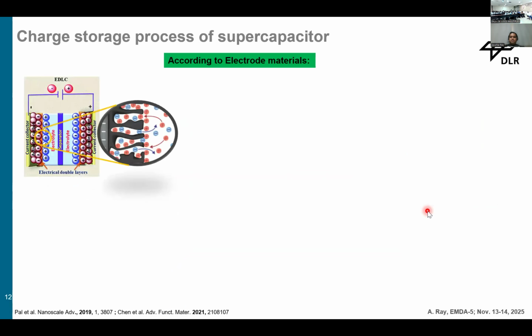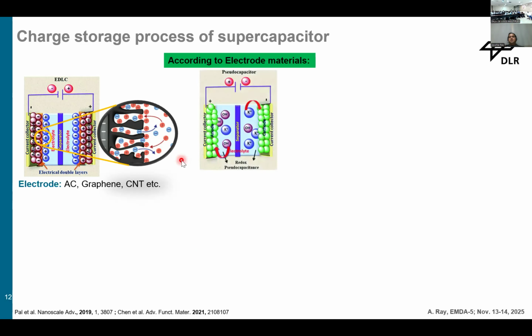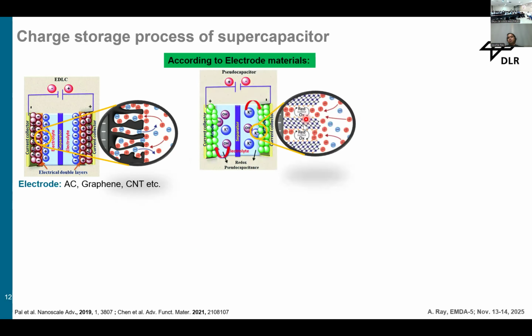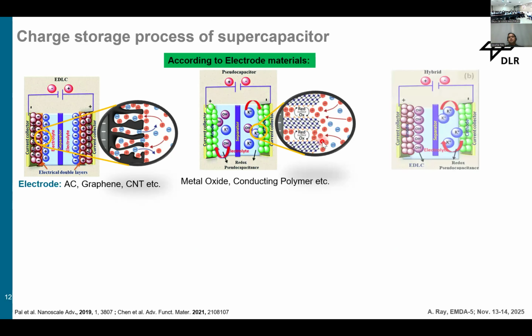Charge storage process in supercapacitors depends on the materials. In carbon based material, charge is stored in an electrostatic way. That means at the electrode interface, you can imagine the ions can be stored in the pores of the electrode material or on the surface. So there is no exchange of electrons or redox reaction, no chemical reaction occurs in the electric double layer. For the redox type or pseudocapacitor electrode material, some redox reactions occur at the electrode electrolyte interface, and there is exchange of electrons. Mainly metal oxides and conductive polymers are used for the pseudocapacitor material, and hybrids. Nowadays, people are making composites with a combination of carbon-based material and metal oxide, different types of polymer, to get the advantage of both the electric double layer and the redox active pseudocapacitor.